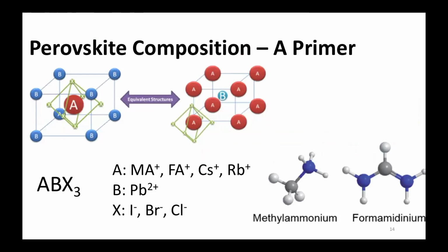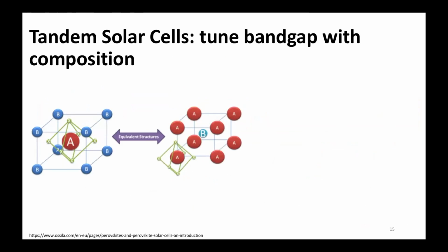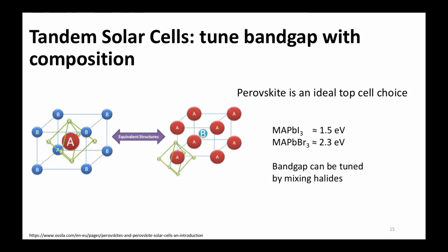You already know about the perovskite structure. So the materials are similar, but they tune the composition for the tandem cells. And that means that they especially put in cesium and formamidinium. So we can tune the band gap of the perovskite layer. If you use methylammonium lead triiodide, you are at 1.5 electron volts. Now, if you use the bromide, then the energy gap is larger. So if you make a mixture, you can tune the energy of the band gap. And you can do that also for the formamidinium and also with the effect of the cesium. You can take it all together. And in that way, you can try to tune it to the optimum.